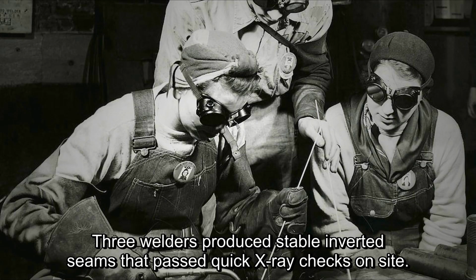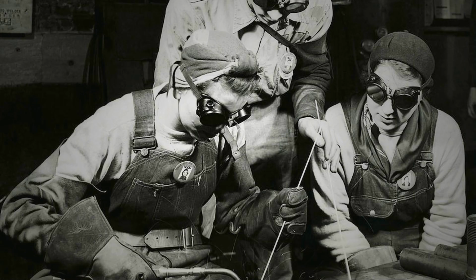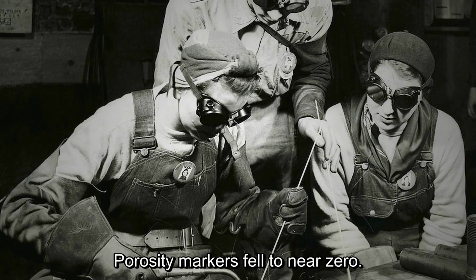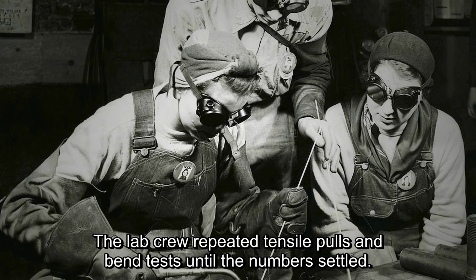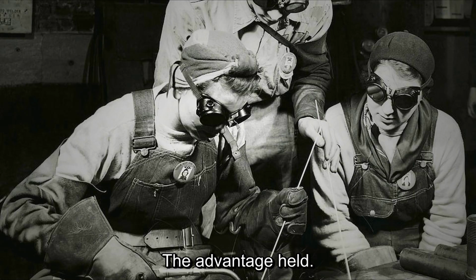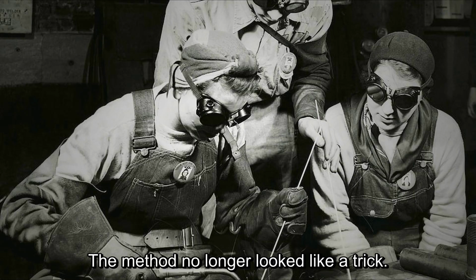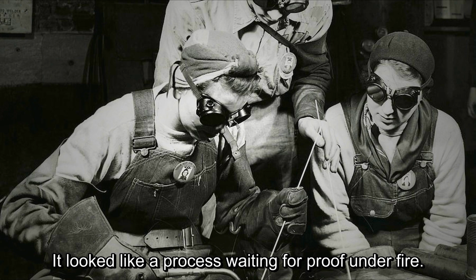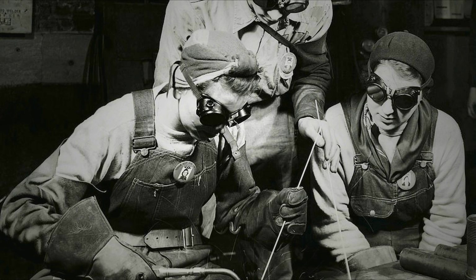With those limits, replication improved. 3 welders produced stable inverted seams that passed quick X-ray checks on site. Slag separated cleanly. Porosity markers fell to near zero. The lab crew repeated tensile pulls and bend tests until the numbers settled. The advantage held. The method no longer looked like a trick. It looked like a process waiting for proof under fire.